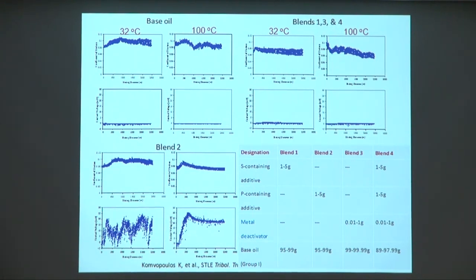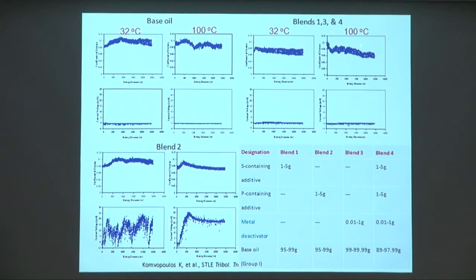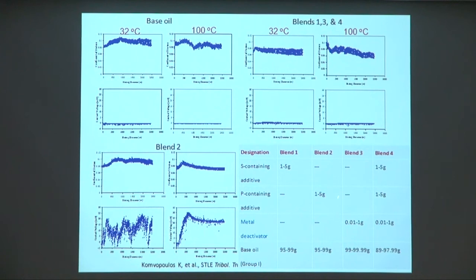But it doesn't mean that the film is not forming, as it is indicated at the high temperature by the sharp drop of the friction coefficient. So we can see here that the film formation is not captured in situ, but it is happening as the friction decrease takes place. But blend 2, which has phosphorus,